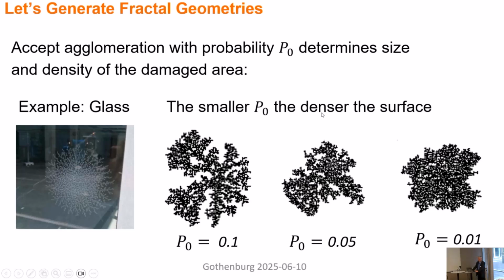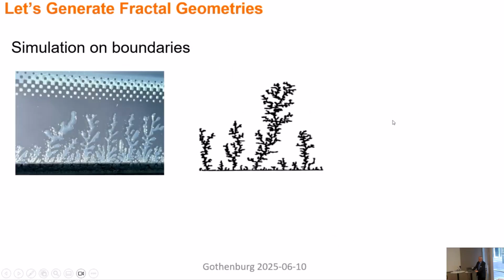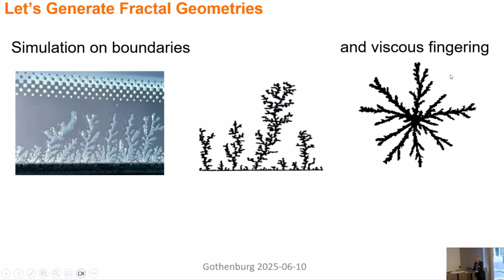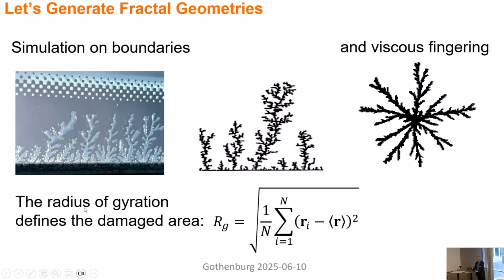The smaller P0, the denser the surface. So we can start also from the edge, then we can see these kinds of patterns. And this is one picture from reality, what reality shows. And viscous fingering is somewhere in the center. And this is also what you quite often observe in structures, glasses, in polymer foils. Then we can also compute the radius of gyration, which defines the damage area. So this is also something for post-processing.